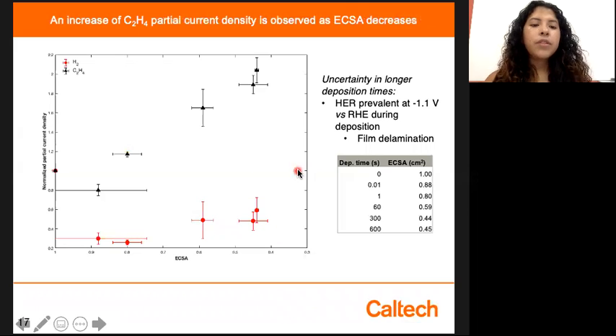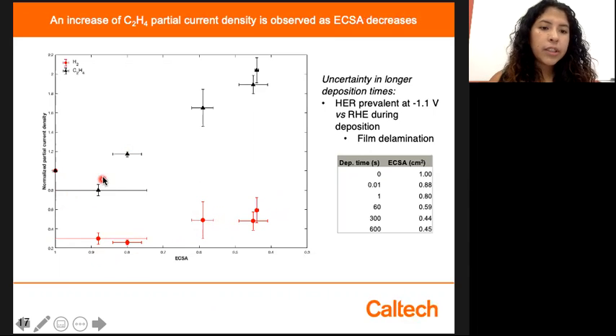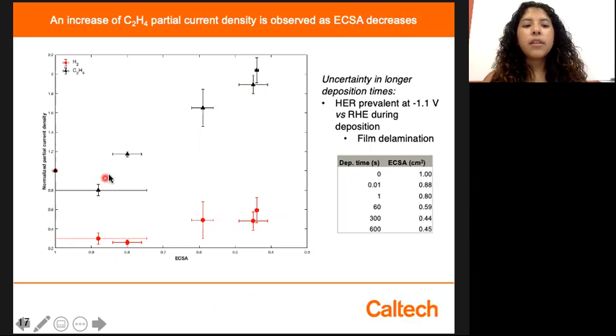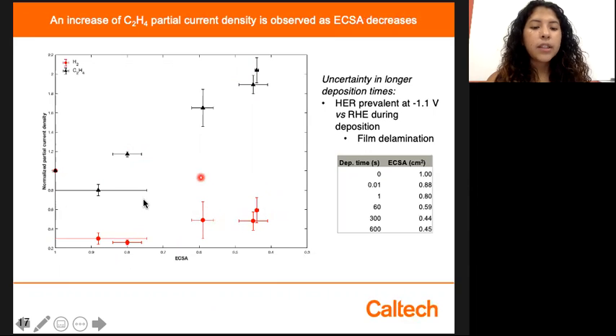But something we found interesting was that although the selectivity continues to plateau, as the ECSA decreases, the partial current density of our products continues to increase. This leads us to believe that even though there are fewer active sites, the few active sites that we do have left become more active, causing this reaction to move forward.